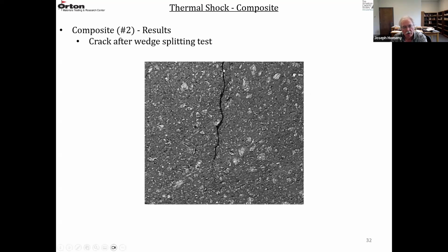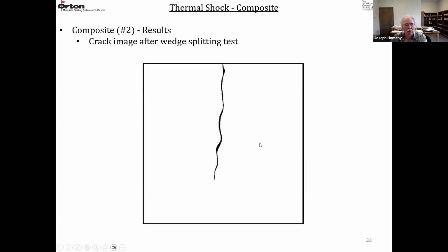This is a higher magnification of that crack that's growing. You can see there's some deviation from linear behavior. There's a MgO aggregate that went around. And then they modeled this.